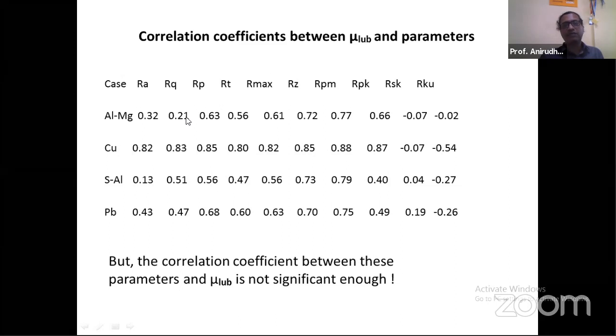And in some cases, when we were fortunate, we got something like 0.8 and 0.7, but it was not guaranteed, which means that these so-called descriptors are not completely sufficient to describe the roughness features of those surfaces that we used, which can explain the friction, or in other words, explain the roughness features which are contributing to ploughing, or the resistance due to interlocking and causing resistance in sliding motion.